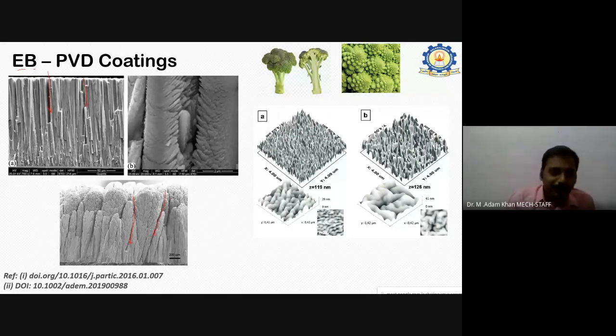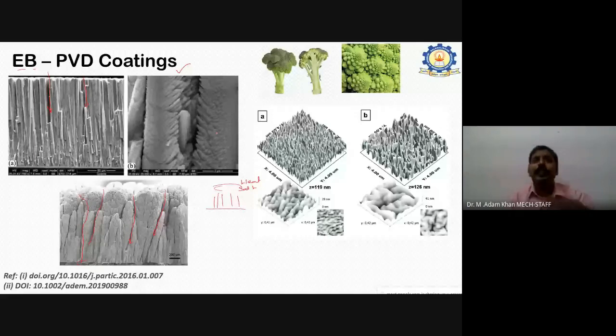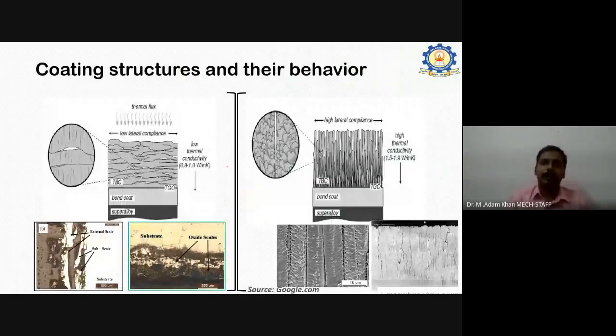So what happens here? When something is left over there, it will take the solution or make the elements pass from here towards the substrate, the adjacent layer. Instead of making direct surface contact, you are making some capillarity to flow along the surface. It may be heat or any salt, to slow down. That's all. You are making the oxidation reaction or corrosion reaction slow down. Nothing more than that. This was the very common practice followed in early days. That is why research turned to making thermal barrier coatings with the help of the thermal spray method. This is the comparison here.